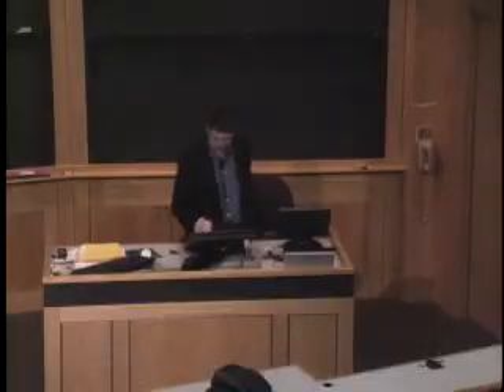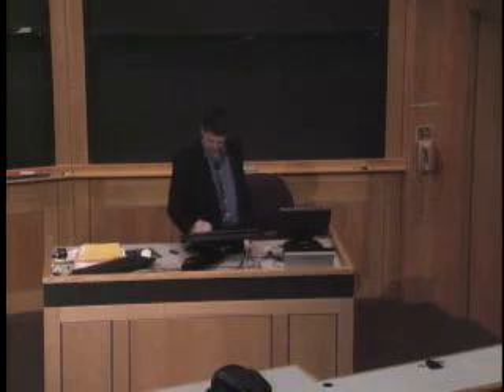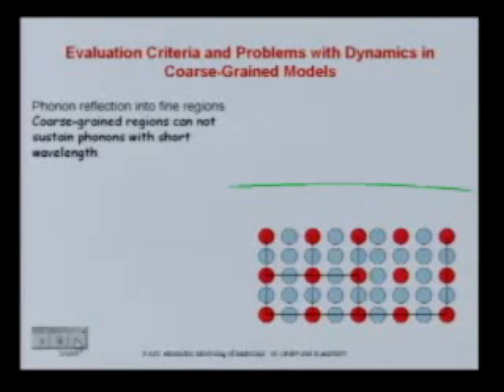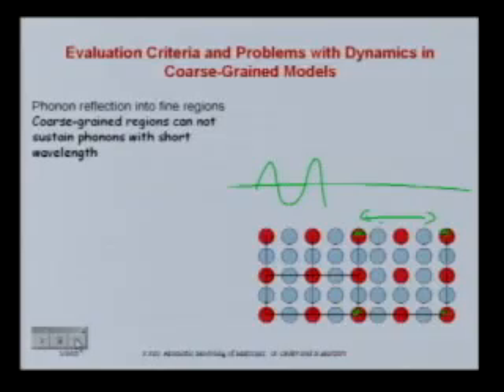Let's say you have a phonon come in here with a wavelength like this. Since here you only have these nodes, this is essentially the minimum wavelength you can have, because it's the minimum bond distance. So every time, at every interface between a fine region and a coarser region, a series of phonons that have a wavelength too short get reflected back because they cannot go into the coarser region. Ultimately, you hit the continuum region and you can't have any phonons.